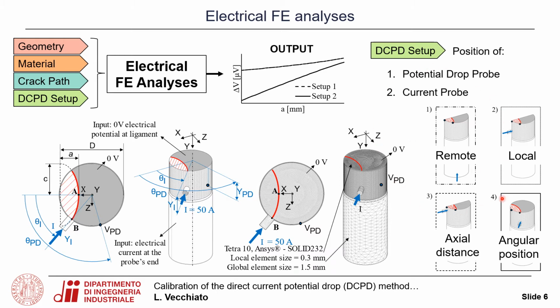The first one was a remote current input, in which the current was injected from the specimen ends. The second one was a local current input, in which the current was injected on the cylindrical surface on the crack symmetry planes. The third model was adopted to check the effect of the axial distance of the current probe with respect to the crack plane. And the last analysis was performed to check the effect of the angular position of the current probe.